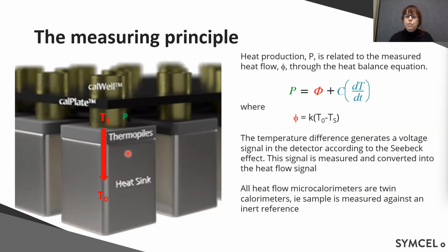And if you have a temperature difference over the detector, it will generate a voltage signal according to the Seebeck effect. So this voltage signal is what we're measuring, and we convert it into the heat flow signal that we are collecting in the software. I mentioned that all heat flow calorimeters are twin calorimeters.